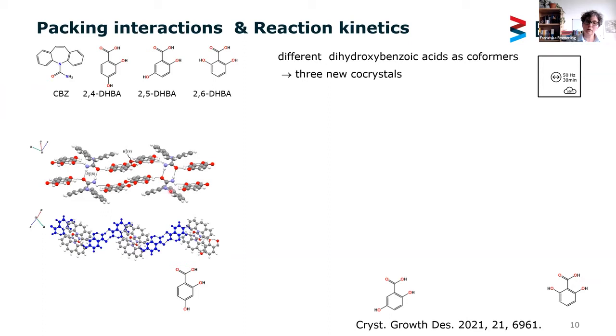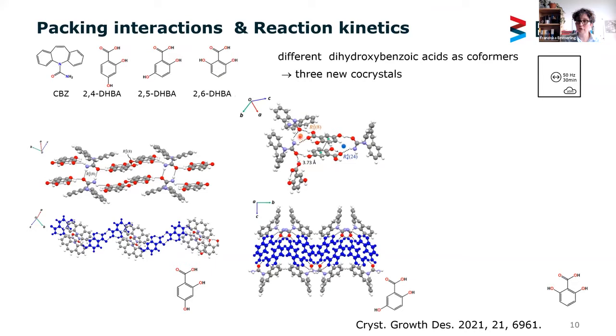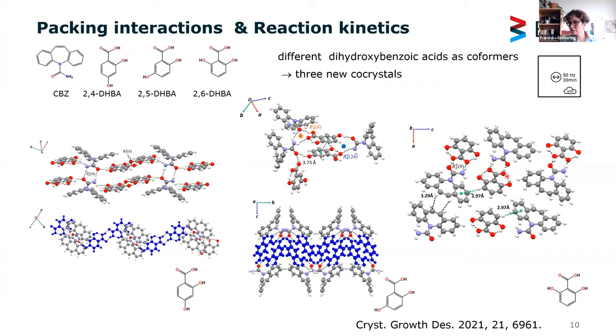So in the first example, this is the 2-4 coformer. We can see that the homosynthons existing in the starting materials, carbamazepine and the acid, are preserved. It changes a bit if we move on to this 2-5 compound, then we see new heterosynthons formed, here marked with orange and blue. And we also have some pi-pi stacking. The result is a more wave-like structure, as you can see here below. And in the last case, we change from our homosynthons to a new strong heterosynthon, which is also well known.